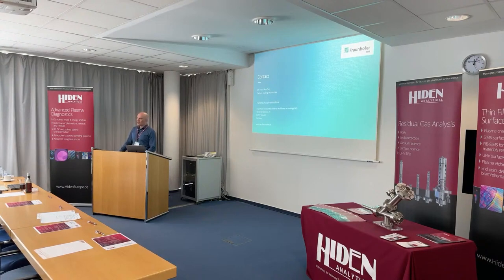It does, yes. Of course, you have the heavy molybdenum. You expect some changes. If you shoot the molybdenum deep inside the carbon, then you have some sp2-rich traces or graphenic traces inside the material, which makes totally different properties. And we did EDX measurements of it. It's working well. Then it's getting more difficult, of course. Another Fraunhofer Institute in the project did XPS measurements of it, doing some sputter depth scan and seeing the distribution of the single elements within the coating depth. And so we also see we do not have the highest amount of molybdenum on the surface. It's 20, 30 nanometers below the surface.